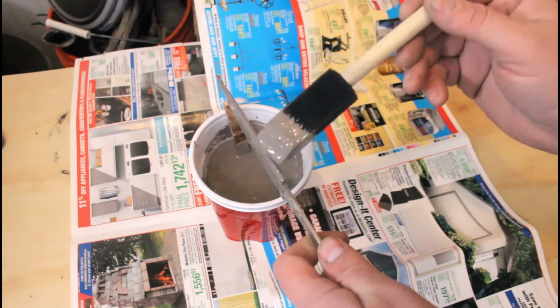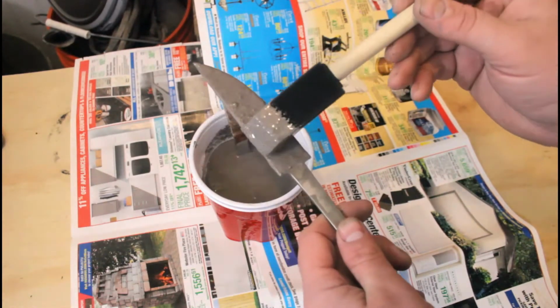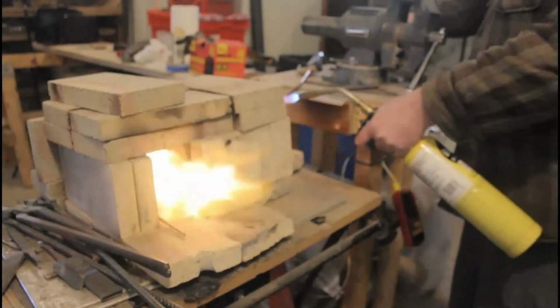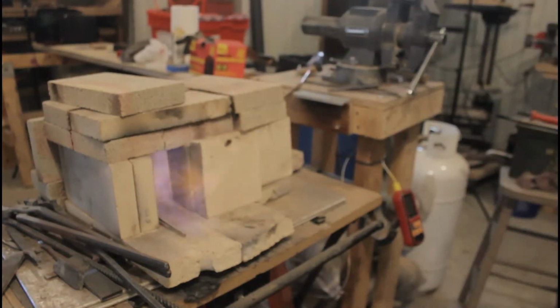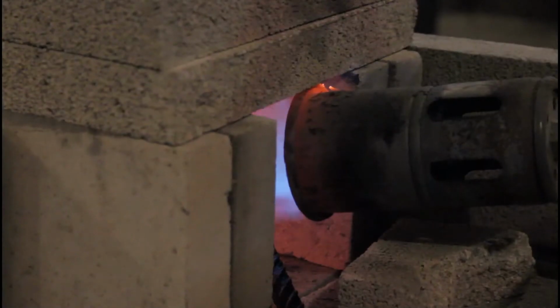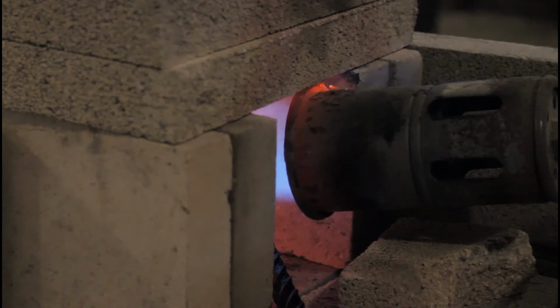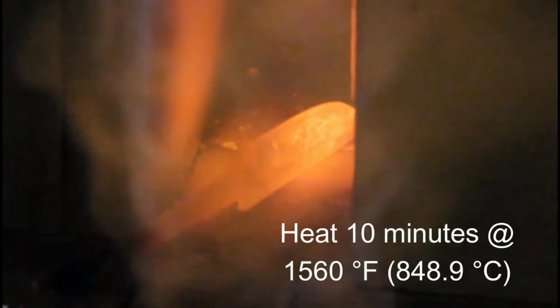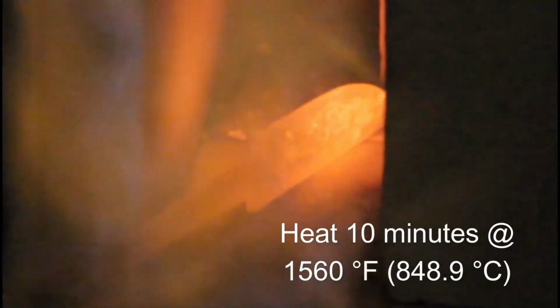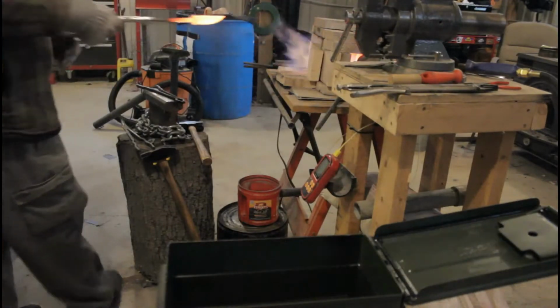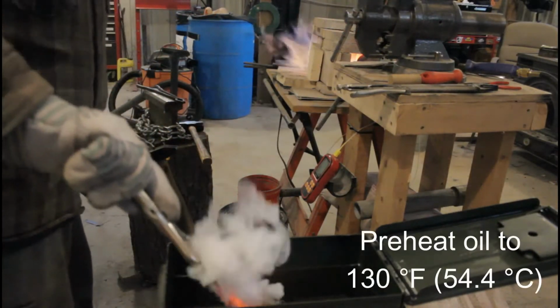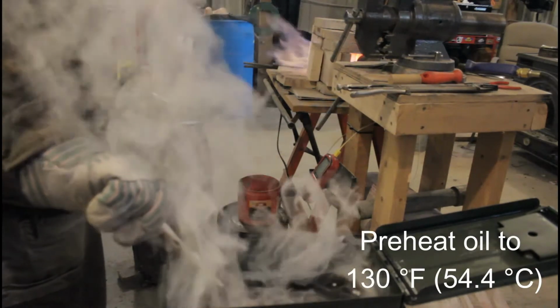I'm hoping that this will make the blade easier to clean up after heat treat is complete. For the heat treat of this knife, I'm using the instructions for the heat treatment of 52-100 steel as adopted from KnifeSteelNerds.com, supplemented with information from Alpha Knife Supply. I'm going to slowly bring the heat up to 1560 degrees Fahrenheit and hold it there for about 10 minutes. After that, it gets quenched in preheated canola oil.